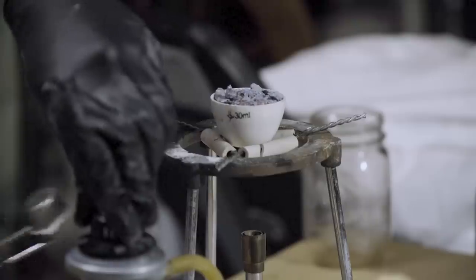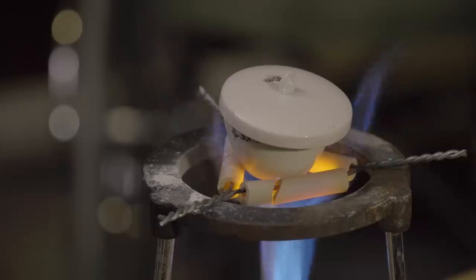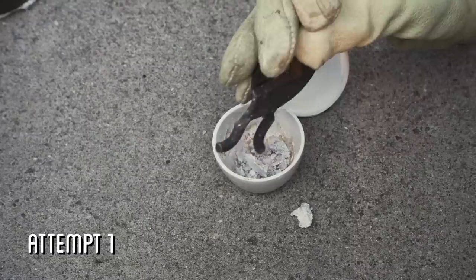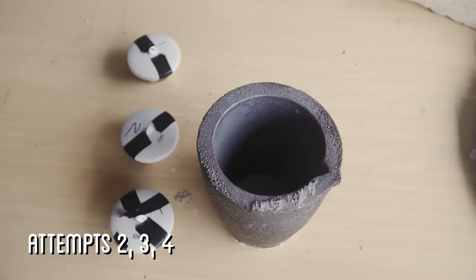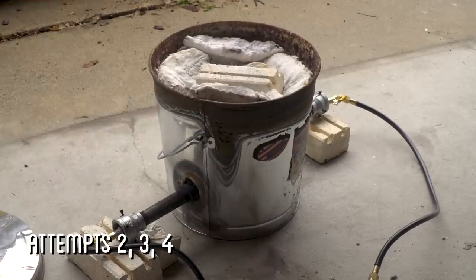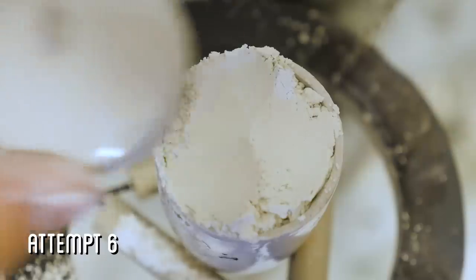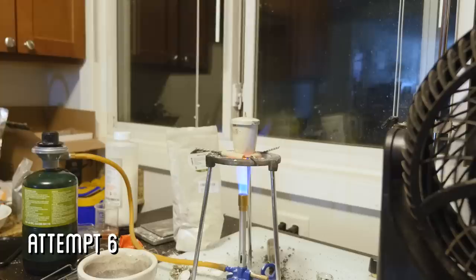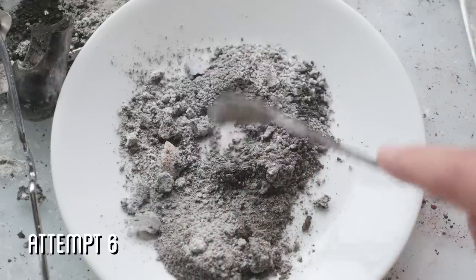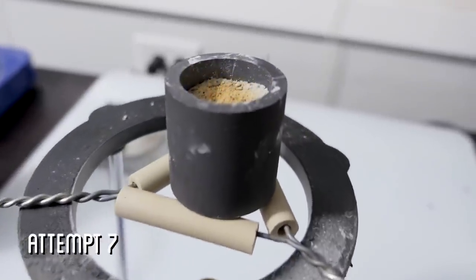The biggest challenge is that the process requires the mixture to be heated and held at a high temperature for anywhere from 4 to 48 hours, depending on which recipe you're following. The forge I had previously built can easily reach these high temperatures, but it's hard to measure the exact internal temperature of the mix and hold that constant temperature. Next I tried small crucibles over a Bunsen burner. This had two problems: first, it was difficult to get the inside of the crucible hot enough for the long duration; and secondly, the crucibles weren't airtight and the sulfur inside would react with the outside air and burn off before it could react with the other compounds in the mix.